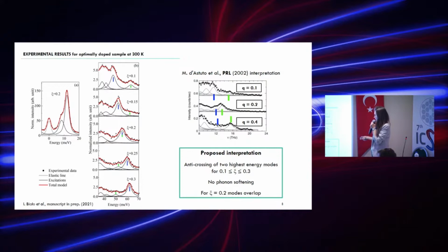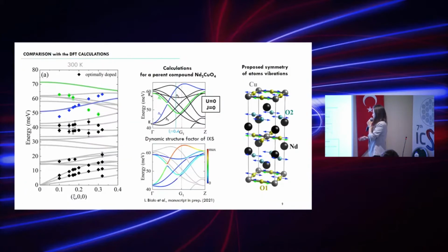up with Q vector. So it means that these two modes cross at a point around 0.2, they overlap at this point, and in our interpretation there is no anomalous softening of the green modes, just crossing of them around 0.2, crossing or anti-crossing. So that's what we propose for this dispersion relation. And the dispersion relation is plotted here on top of DFT data, because to be sure that our interpretation is okay, we performed calculations.